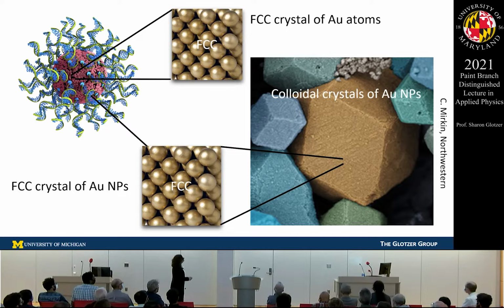Each one of these little tiny dots is a gold nanoparticle. If you were to blow this up, you'd see that these nanoparticles are arranged in a face-centered cubic arrangement. And if you were to blow up each of the nanoparticles, you would see that inside are gold atoms that are also arranged in a face-centered cubic crystal structure. So you have this really cool hierarchy of organization. Of course, the nanoparticles could be any kind of crystal structure relative to whatever crystal structure this is. But that's a very interesting thing, because then you can achieve different properties on different scales by controlling the organization of, say, atoms within the nanoparticle and then controlling the organization of the nanoparticles into some larger scale structure.